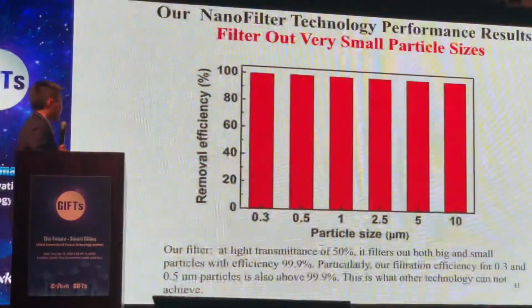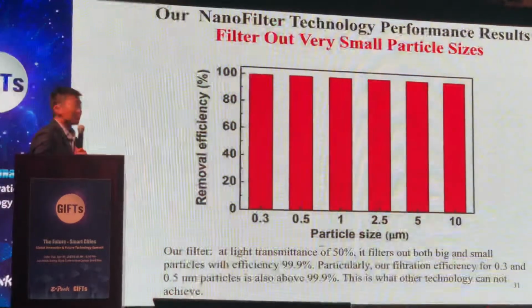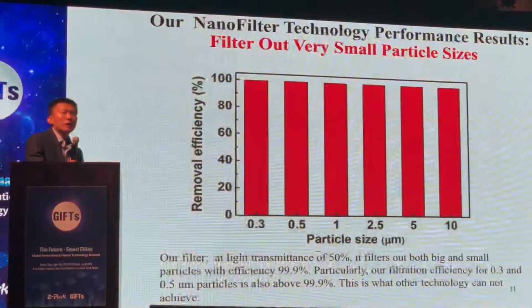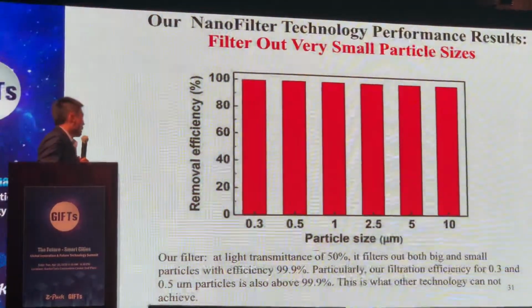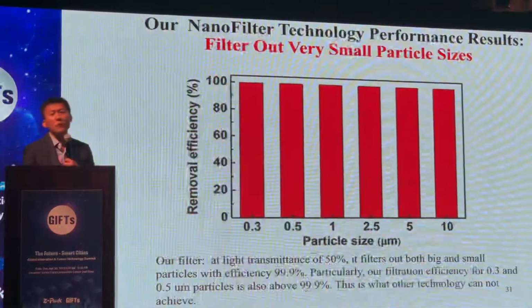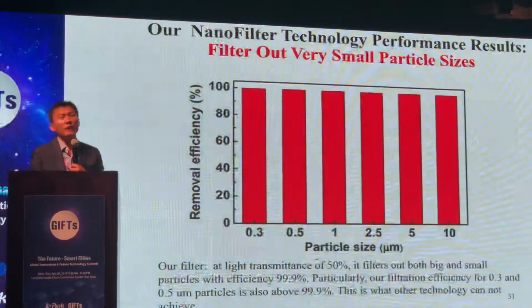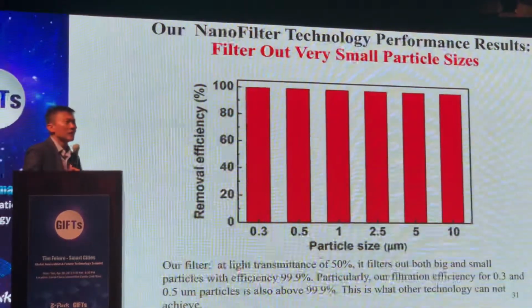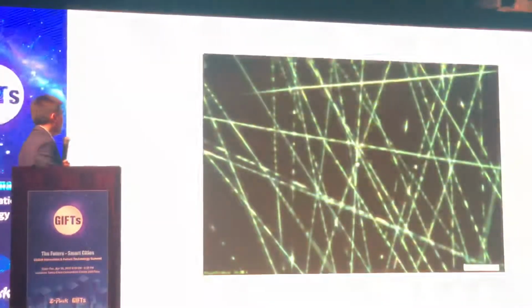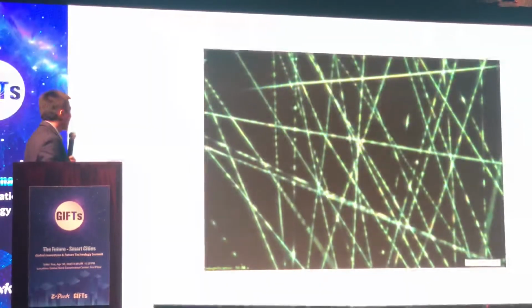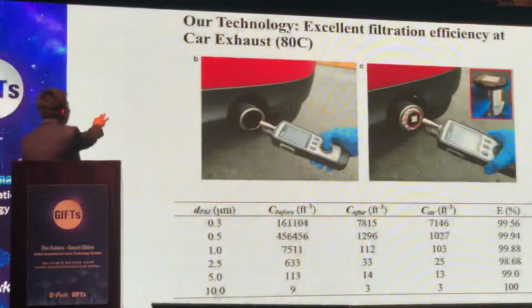So with a technology like this, we actually did all the study, it can filter out not only 2.5 micron and 10 micron, but all the way down to 0.3 micron. So it also can filter out bacteria and viruses with high efficiency. A technology like this really allows us, I'm going to skip this slide, to do something like this,